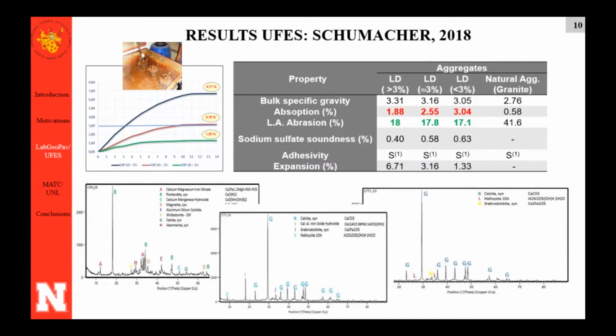Also, the Los Angeles abrasion was much better than the natural aggregate because it was a much stronger material than the natural aggregate that we have in Brazil. We do have natural aggregates in other parts of the world that have better Los Angeles abrasion, but what we have now that are being used in the construction of our roadways are these natural aggregates with 41% Los Angeles abrasion, and slag is a much stronger material, with much better Los Angeles abrasion. So this is also a good result for us.